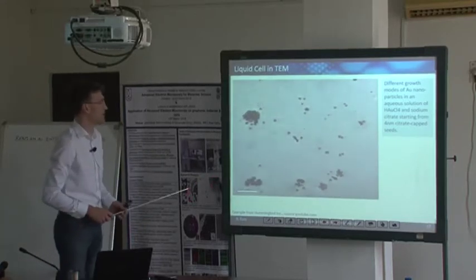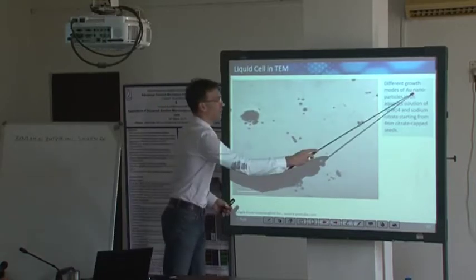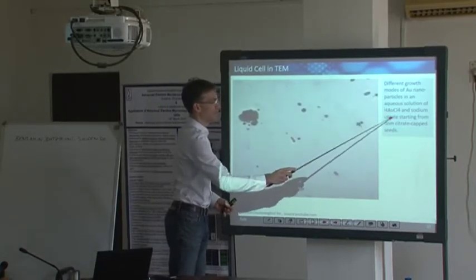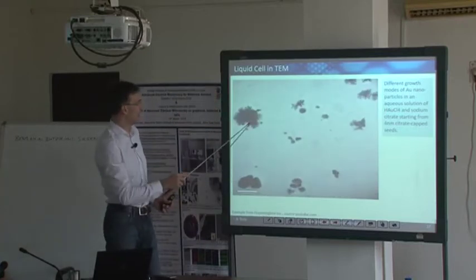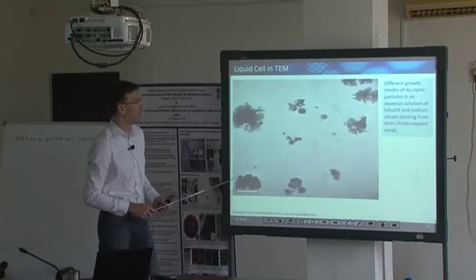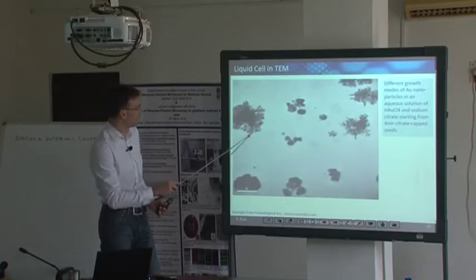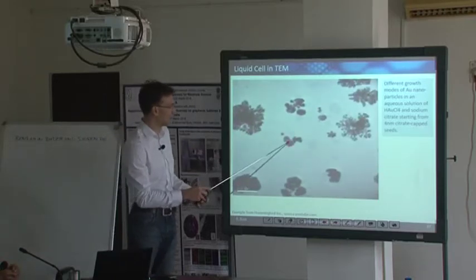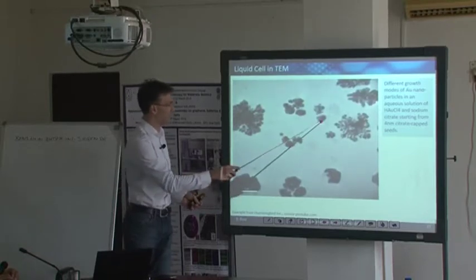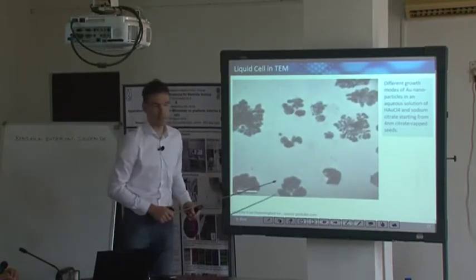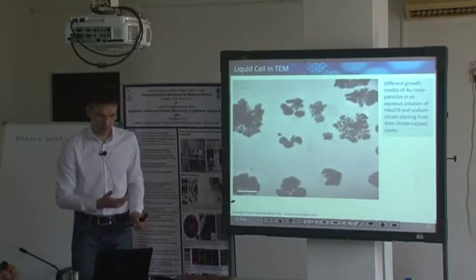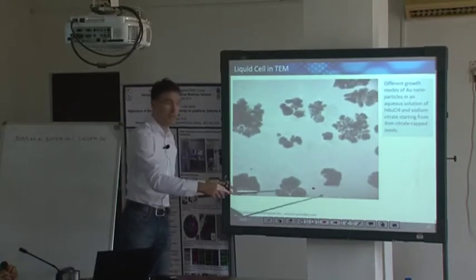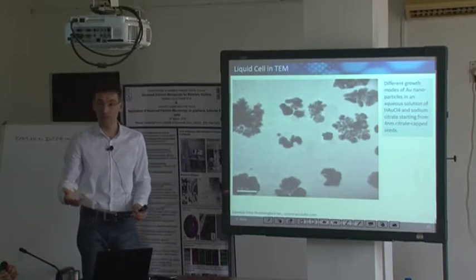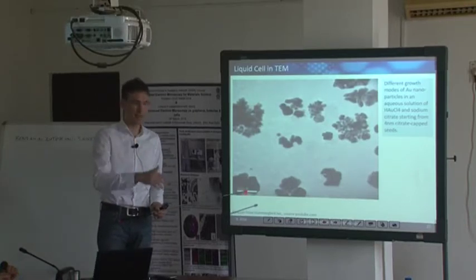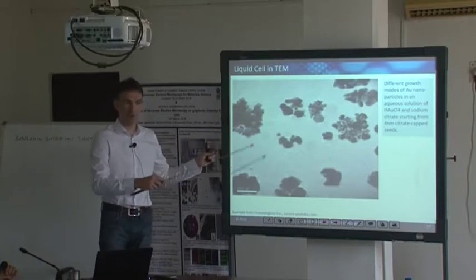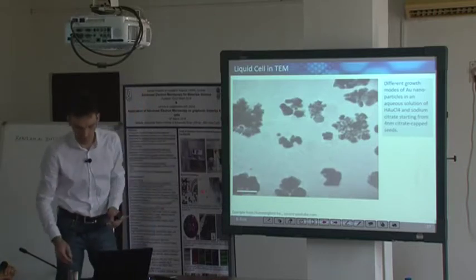This is the growth of gold structures from a solution and some reaction educts, and you can see that there are somehow different growth modes of these dendritic structures in this particular case, and of this continuous growth, let's say, of more homogeneous nanoparticles. And if you just see the final state deposited from a solution onto your TEM grid, you might not understand what's going on and why those different structures form.